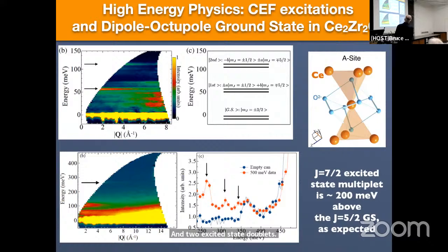And you can pretty much read off the eigenvalues from the data, because there's a magnetic excitation here, and a magnetic excitation here, and you only expect 2 out of the ground state. So the eigenvalue part of the problem is solved. The eigenvectors, which are the wave functions, you get by actually modeling how much intensity goes into the first transition compared to the second transition, and cross-reference that with the Van Vleck susceptibility, which depends on these answers, okay? Anyway, all of that can be done. The eigenvalue problem can be solved. You could probably solve it, given half an hour or so.